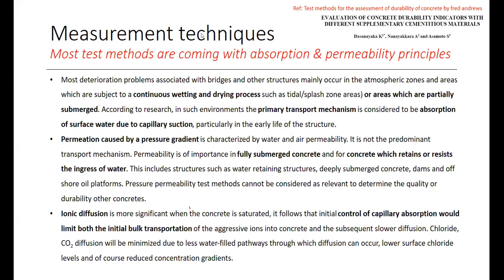So basically, we have published a paper together with Professor Nanayakkara on the studies of that transport mechanism inside concrete, how a material can transport inside concrete. Not only us, but most researchers also found the same finding: most deterioration problems of bridges and other structures happen basically due to continuous wetting and drying processes. In our country, we have about 6 months of rain and 6 months of dry, with intermediate raining, so it is somewhat like a wetting and drying process. Those areas, or partially submerged areas, usually have absorption as their primary transport mechanism. It happens due to capillary suction forces.